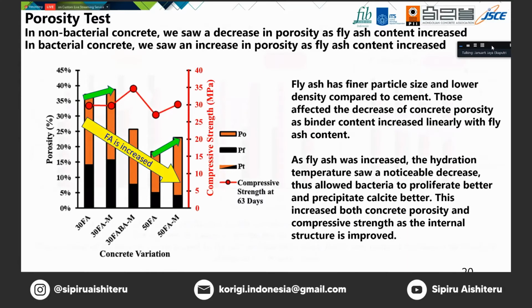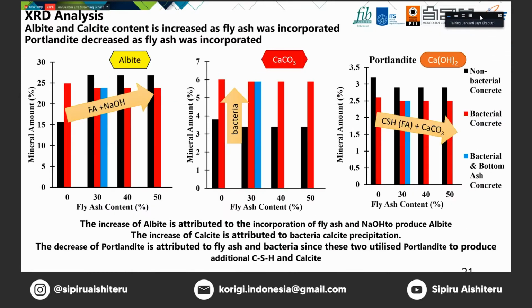This one. Albite, as a product of aluminosilicate, reacts with the reaction product between sodium hydroxide and fly ash in the early age, and increases as the fly ash is present in the mixtures. The product of bacteria was also found, as we can see that there is calcium carbonate content in the result, especially with the red specimen containing bacteria.